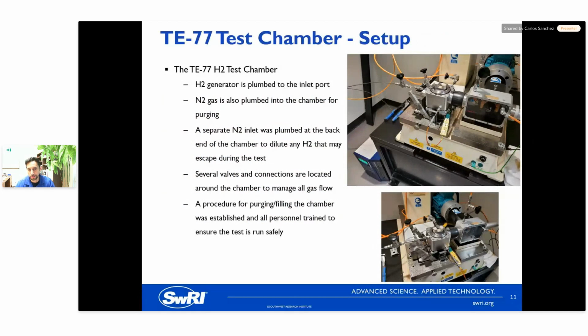Like I said, we have a series of linear lip seals that help to mitigate that leakage. But in case it does happen, we have nitrogen plumbed in the back to dilute any hydrogen that may escape. And of course, that is going outside into our scrubbers outside the room to make sure that's all taken care of. There are several valves and connections located around the chamber to manage all the gas flow. There are also some pressure transducers there to monitor the pressure.